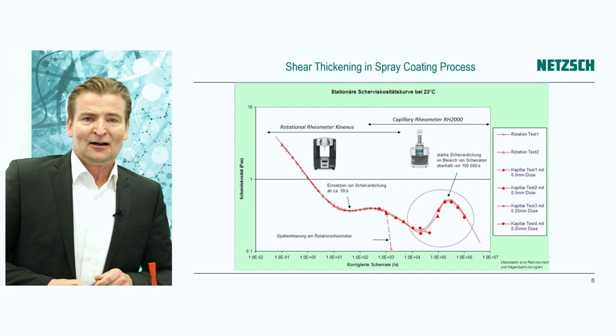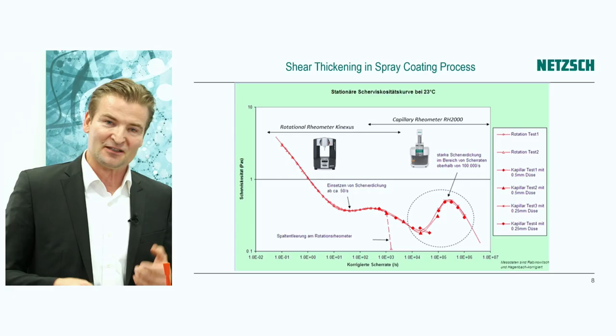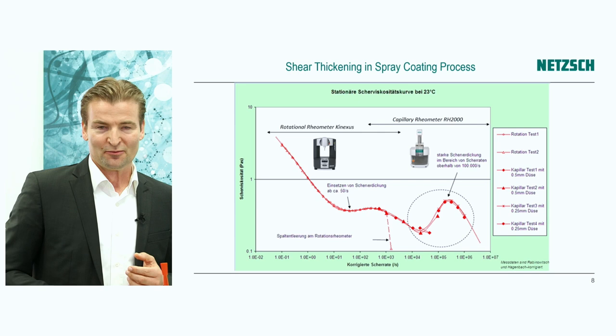This is an example for spray coating, showing the high shear behavior of a material under shear rates up to 10⁶ reciprocal seconds. You can see two stages of shear thickening: viscosity increases at mid shear rates, and again at the high shear rates where spraying occurs. This coating cannot be sprayed — it will block the die. Customers therefore examine the high shear rate region for any onset of shear thickening. It also creates hysteresis in the flow properties, so it must definitely be avoided.